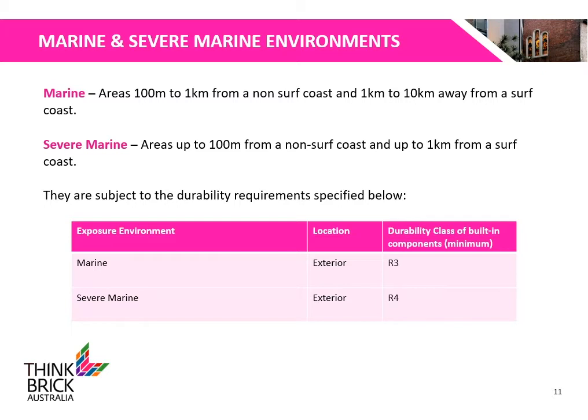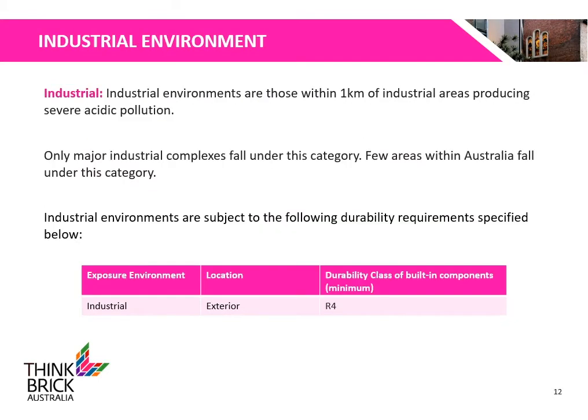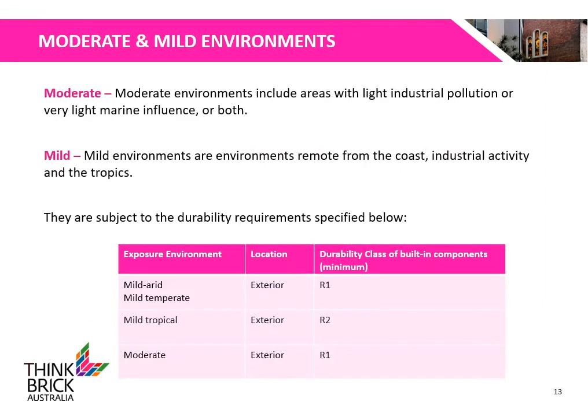The minimum durability classes for marine and severe marine environments are specified. Industrial environments are defined as areas within 1km from a major industrial complex producing severe acidic pollution, and R4 classed built-in components shall be used for these areas. Moderate environments are areas with light industrial pollution or very light marine influence, or both. Mild environments are areas remote from the coast, industrial activity, and the tropics.